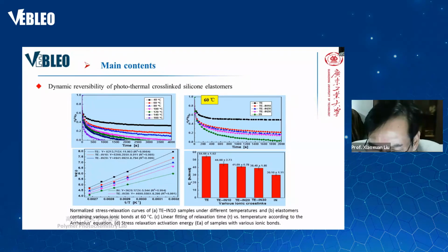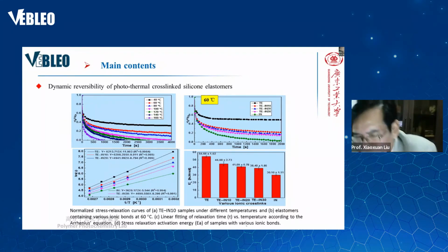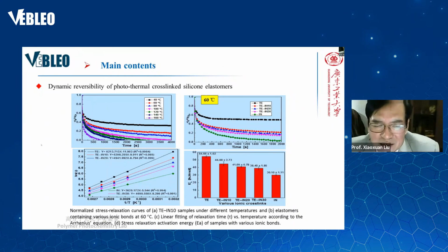C is the fitting of the relaxation time toward temperature according to the Arrhenius equation. D is the stress relaxation activation energies of the samples with various ion bonds. So this is the picture, and the regular changes in every picture or every curve.